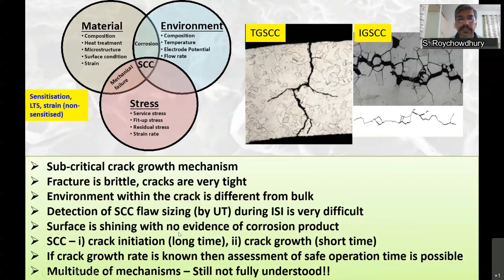In SCC, the lifetime is composed of two parts. One is the crack initiation time, which takes up the majority of the lifetime, almost 90%. But once initiated, the crack will grow; the remaining 10% of the life is taken up in growth of the crack, which is very fast. However, even if you have SCC cracks present, you need not replace the component. You can live with cracks as long as you know the crack growth rate. If you know the crack growth rate, you can estimate how long it will take the crack to grow from, say, A1, which was sized during in-service inspection, to a critical crack length during normal plant operation. Then you can plan your plant shutdowns accordingly.